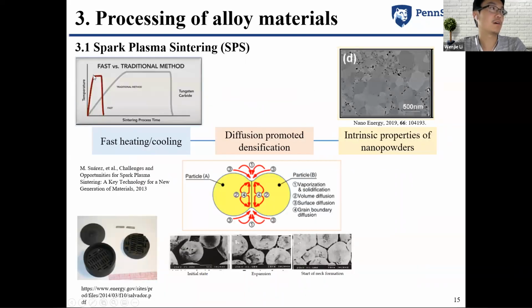So this is one example of SPS as compared to the traditional sintering method. With a high heating and cooling rate, we can finish the sintering in a couple of minutes. In that case, through diffusion-promoted densification, we can maintain the intrinsic properties of the nanopowders, which is important for the improvement of the mechanical properties of the alloy materials. And this is how it looks during SPS sintering. The particles are connected neck by neck at the beginning, and with this diffusion-promoted densification, the particles connect to each other at the end, making fully dense bulk materials.